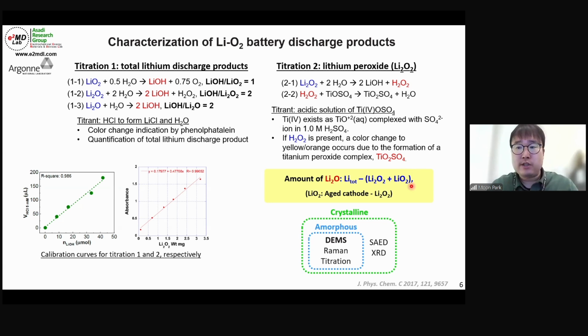Once we age the discharged cathode either in argon or vacuum, the lithium superoxide typically disproportionates to lithium peroxide. So we can prepare two different discharged cathodes: one fresh, right after the discharge, and the other aged. After the second titration, quantifying the amount of peroxide, there's going to be a difference in the amount of peroxide, and that difference exactly comes from the disproportionated lithium superoxide. Once we obtain all three, we can quantify the amount of lithium oxide, Li2O, after the four-electron reaction, approximately but a little more accurately than other methods.